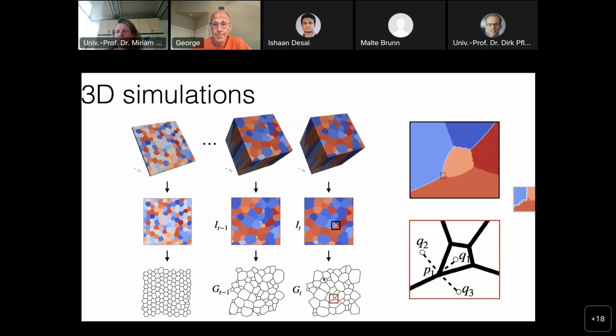Okay. Once we have this representation, the idea is to predict the motion of these junctions as the grains solidify or merge or grow. These vertices are going to be moving. So essentially, we will have a regression problem, trying to predict the position of these vertices. However, the big challenge is that there are topological changes. Not only do the vertices of this graph move, but we also have merge events. For example, this grain here does not show up anymore in this graph. And this grain here is shrinking, and after a few time steps, it's going to disappear. That means that certain nodes and edges disappear from the graph. And so we have to capture this kind of discontinuous topological change.